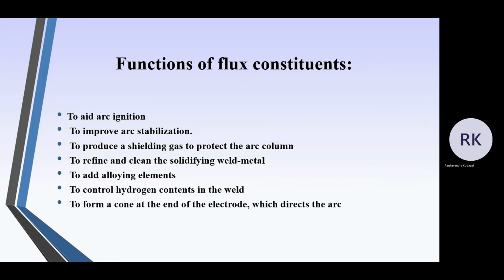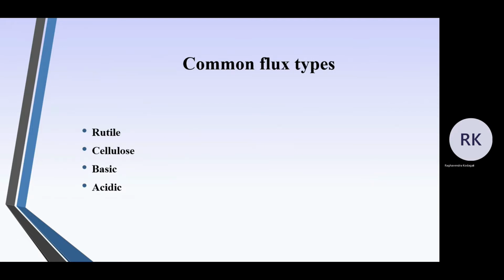Function of flux is generally to aid the arc ignition, to improve arc stabilization, to produce shielding gas, to protect the arc from the air and other disturbance, to refine and clean the solidifying weld metal. That also is one of the important elements. Then to add alloying elements to the weld, then to control hydrogen content in the weld, and to form a cone at the end of the electrode which directs the arc. So that is also the important aspect of functions of flux. So common flux types are rutile, cellulosic, basic, acidic.